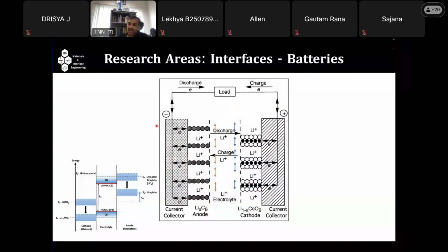So when you have such a charging process, by applying the negative terminal of your external battery to the anode of the battery and the positive to the cathode, after full charging you will have LiC6 and a lithium-poor cathode. Complete removal of lithium from the cathode is almost impossible. Now, in that kind of situation, if you look into the energetics of the battery electrodes, you will have such a situation. So the Fermi level of lithiated graphite is quite higher than this Fermi level. When you connect externally,